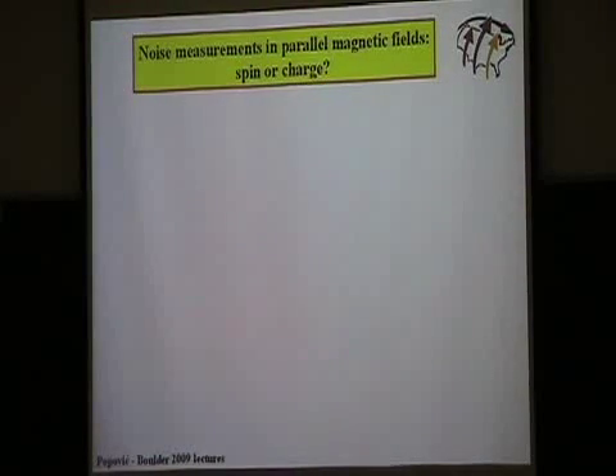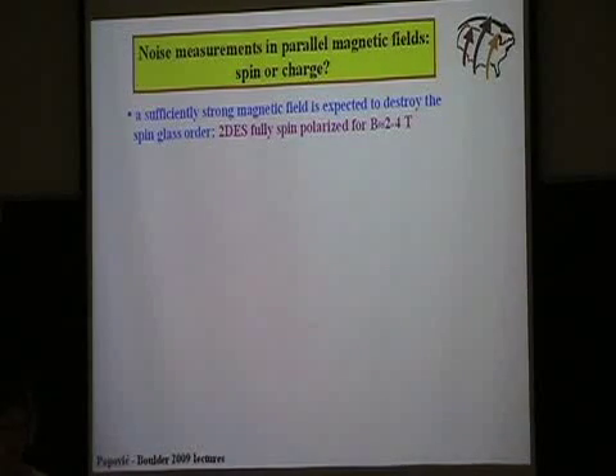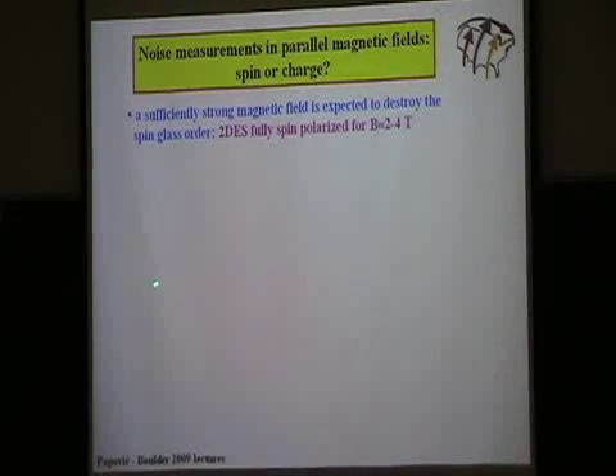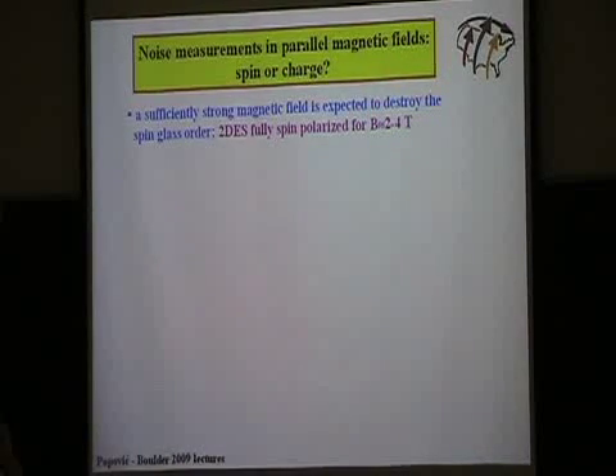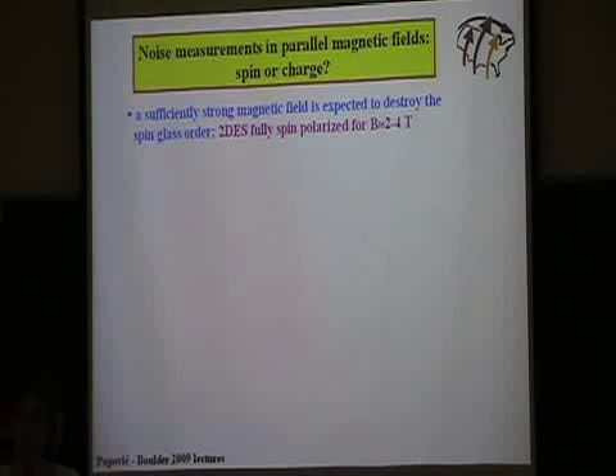Okay, we come to the magnetic field now. So I told you we have a simple system. We have electrons. They interact with Coulomb interaction. They feel the random potential, but electrons also have a spin. So in order to narrow down whether this glassiness is due to the spin or charge degrees of freedom, we perform measurements in a parallel magnetic field, because that way we get rid of orbital effects and the field couples only to the spin. And it is known that in conventional spin glasses, a sufficiently strong magnetic field can destroy the spin glass order, and it does. And we also have the advantage here that a lot of other people have studied these same samples, and they determined that at relatively low fields in this range of densities, all the electrons can get fully spin polarized. So they all point in the same direction, so it's like having a system of spinless electrons.